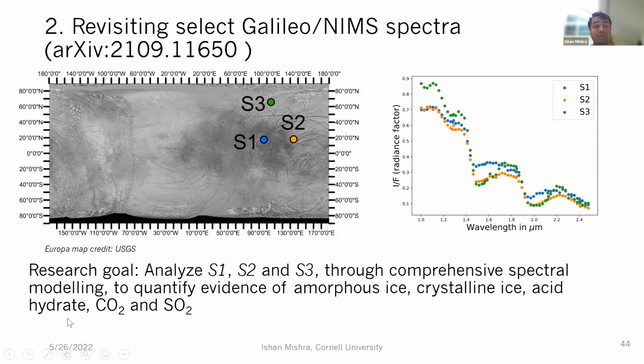Acid hydrate, so this was sulfuric acid hydrate. And as I had mentioned, sulfuric acid is something that is thought to be the primary component of regions where most of the sulfur bombardment is happening. So basically the trailing hemisphere of Europa, and theoretical estimates or laboratory experiments show that when you bombard water ice with charged sulfur particles, the reactions that happen result in sulfuric acid hydrate as one of the dominant equilibrium products. And so that's why we chose that as the non-water ice component.